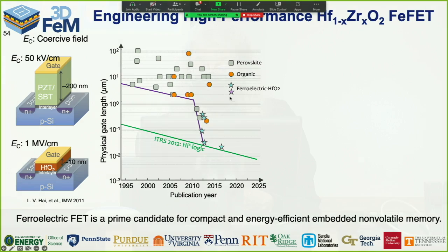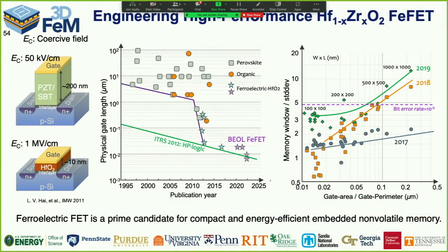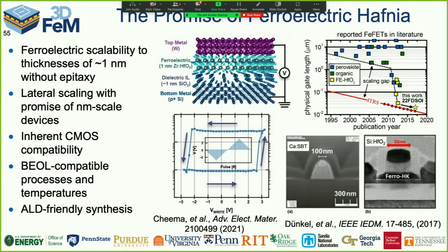The hafnium zirconium oxide materials are scaling like the rest of the processor scales, so that you can actually make scaled devices. So people are very excited about this and are exploring it for a number of different applications. So it's very cool that it's scalable. It remains ferroelectric to 1 nanometer. Oh my goodness, that's pretty impressive. That's a scaled device. Lateral scaling is easy. Hafnia has been the gate material as an amorphous material for the last 10 years. The semiconductor industry is like, this is a material I'm very comfortable working with.